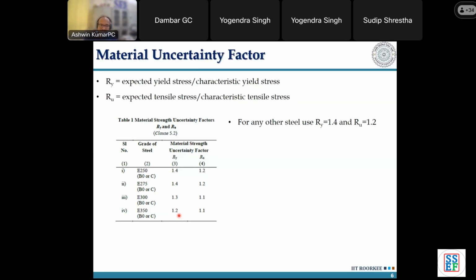If you have any other steel other than E250, 275, 300 and 350 but less than E350, then for that particular steel you can use an Ry value of 1.4 and Ru of 1.2. This is a value that the code says: if you don't have much information regarding the grade of plate that you have, kindly consider the higher end values of Ry and Ru, right?